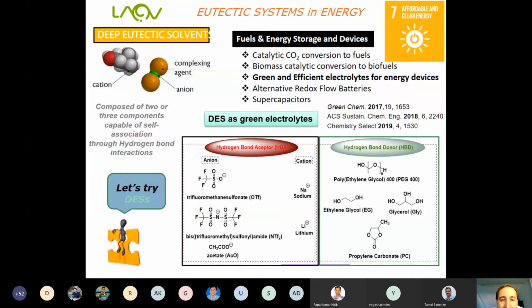And if we move again to eutectic systems, it's possible to use eutectic systems in energy. And in 2017, we proved that deep eutectic solvents can be interesting as green electrolytes. It means we can replace the ionic liquids that I showed you before by deep eutectic solvents.